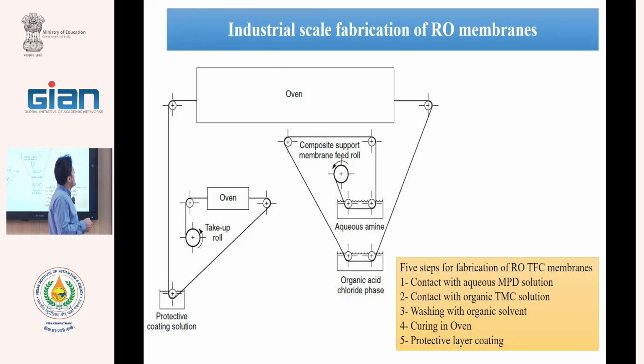In this industrial scale, we have also these steps. We have a polysulfone support previously fabricated by phase inversion on the fabric. First, the roll is fed into the aqueous amine bath, and with the speed of opening and the length of this bath, we control the time of contact. Here it enters the bath, and here it exits. This distance and speed of opening can control the contact time: 1 minute, 5 minutes, or 10 minutes.